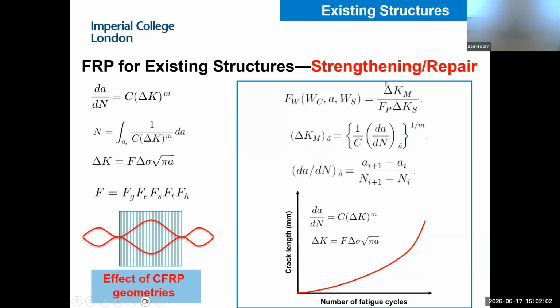The effect of CFRP geometry has already been included in this stress intensity factor. How can we isolate it out? We divide the real intensity factor by the theoretical intensity factor of the steel plate only, which you can calculate for the steel plate without CFRP strengthening. In this way, you can isolate the effect of CFRP geometry.